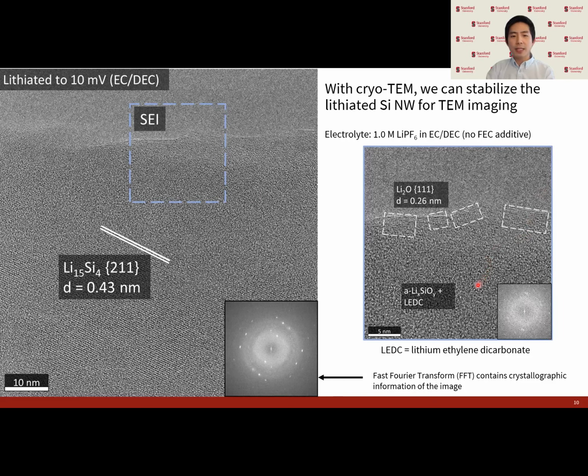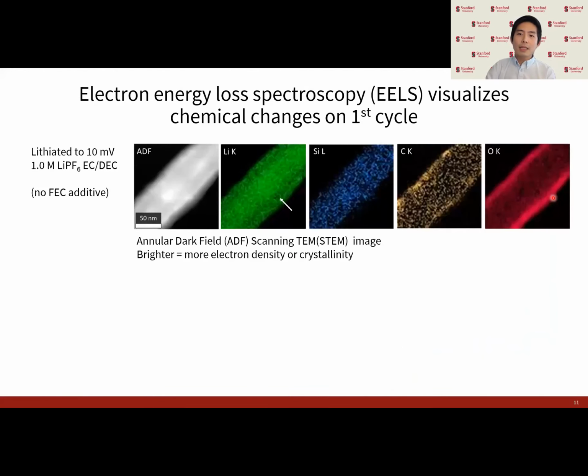And these amorphous components are coming from the lithiated silicon oxide, so lithium silicate, along with LEDC, so that's lithium ethylene dicarbonate. And this lithium ethylene dicarbonate is an organic carbonate that comes from the reduction of ethylene carbonate, the solvent. Now, high-resolution TEM images like the last image are sensitive to crystalline components, but the amorphous boundaries are harder to visualize. But like we mentioned before, the TEM is a good spectroscopic tool. And by operating the TEM in scanning TEM mode, or STEM mode, coupled with electron spectroscopy methods like electron energy loss spectroscopy, or EELS, which is very nice because it's sensitive to light elements like lithium, we can start to map out these boundaries in these lithiated silicon nanowires.